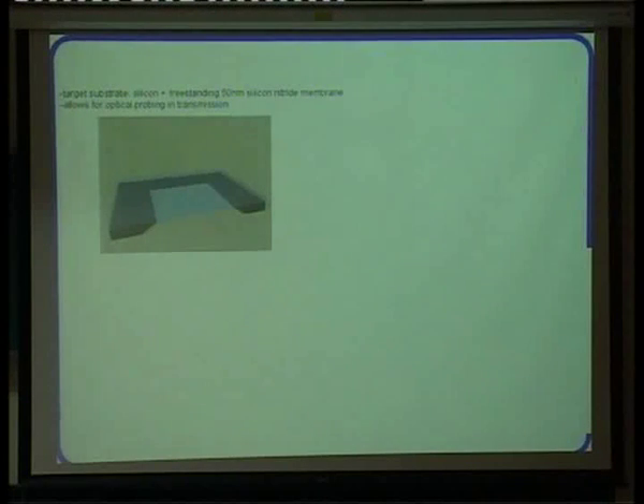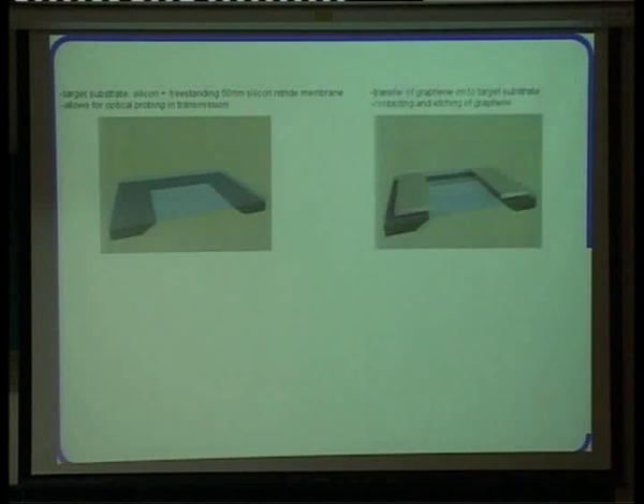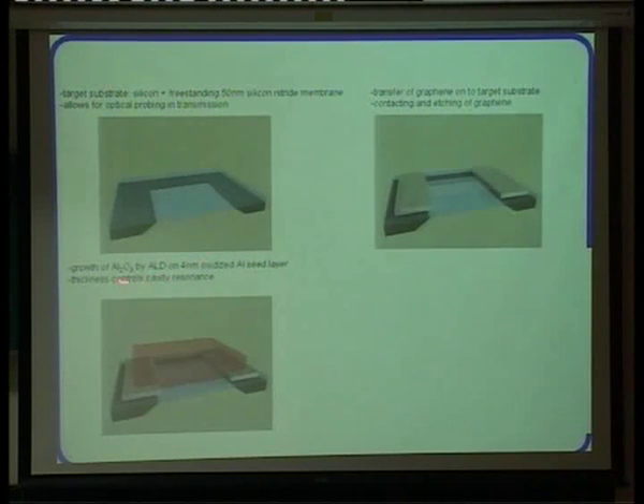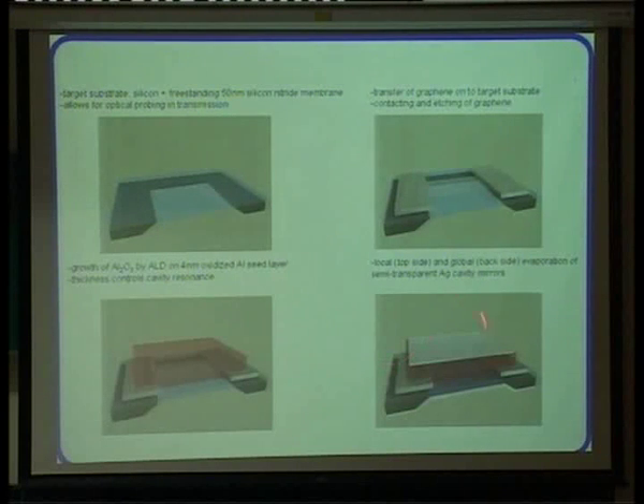To do that takes some time, but as I mentioned at the beginning of the talk, everything can be done now. So you take a silicon nitride membrane, which is semi-transparent. You put graphene on the top. You also put source and drain contacts. Then you grow by ALD some aluminum oxide. And then you have to deposit the mirrors, the semi-transparent mirrors, on the top and at the bottom. And then you have your cavity.